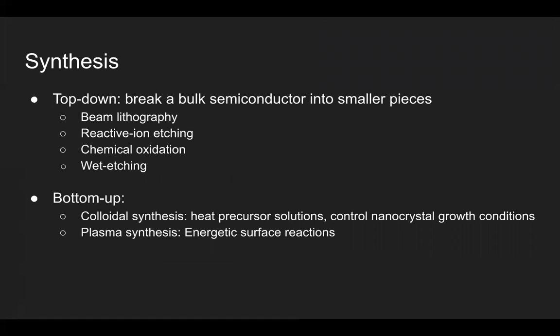Quantum dots are synthesized in methods that fall into one of two broad categories, top-down and bottom-up. Top-down methods break down a bulk semiconductor into smaller pieces and involve methods such as beam lithography, reactive ion etching, chemical oxidation, and wet etching. The problem with top-down methods is that they often introduce impurities that are undesirable for the devices that we're working with.